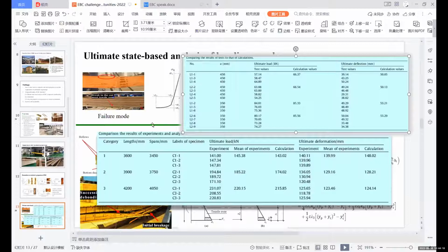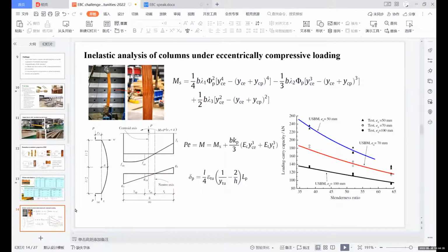So we compare the prediction results to the test results. So a good agreement can be achieved. Next. So this picture shows the combined bending and compression members. So we developed a model to predict the load carrier capacity of the beam columns. So here we compare the modeling results with the test results. So we also get good agreement between them.